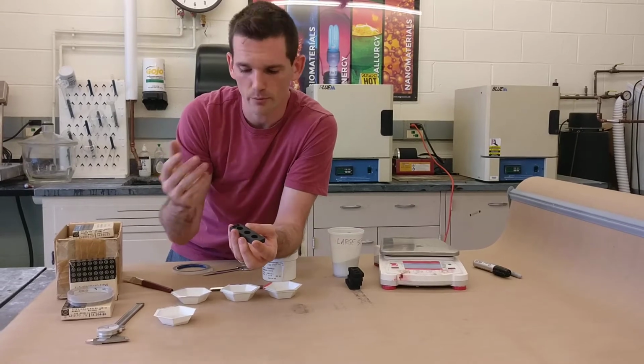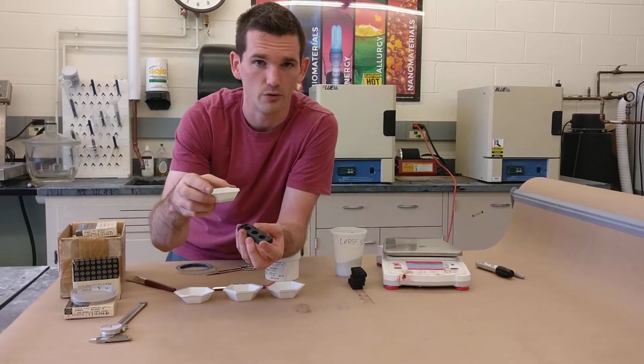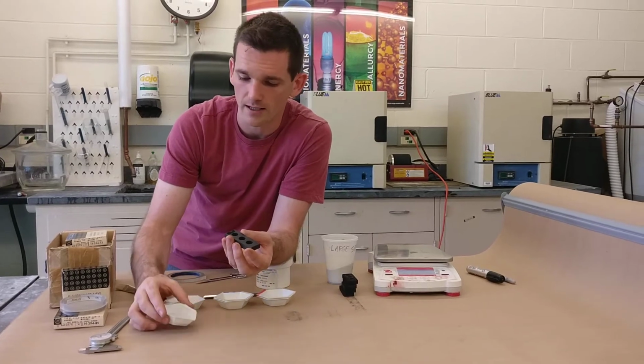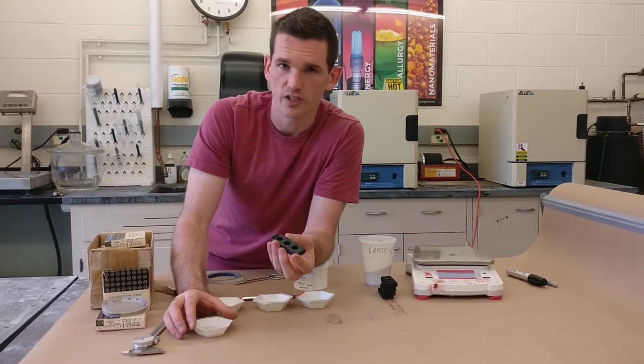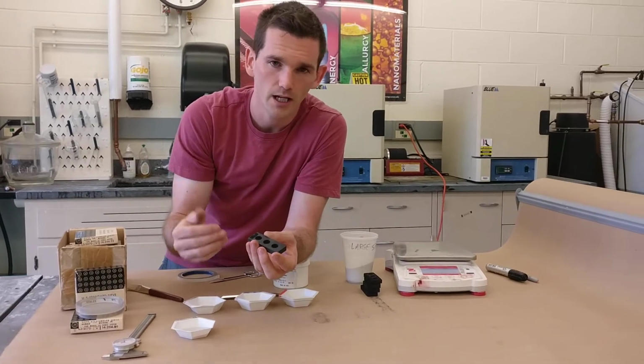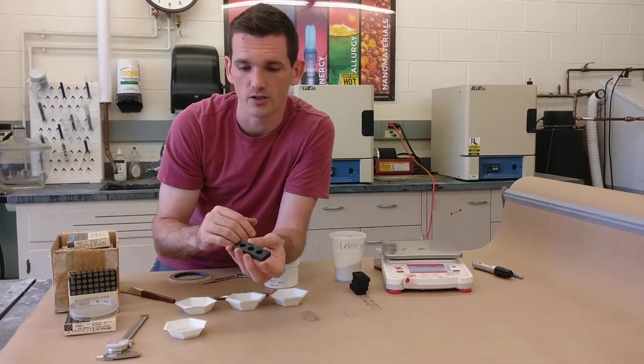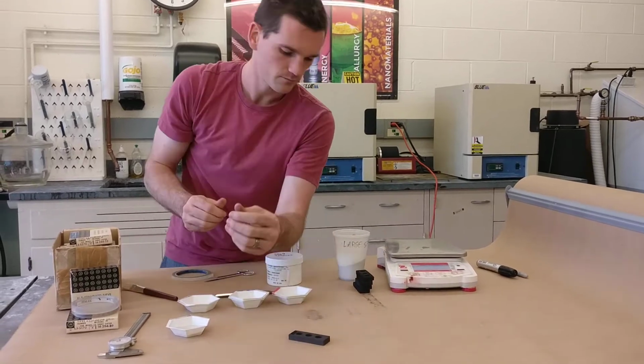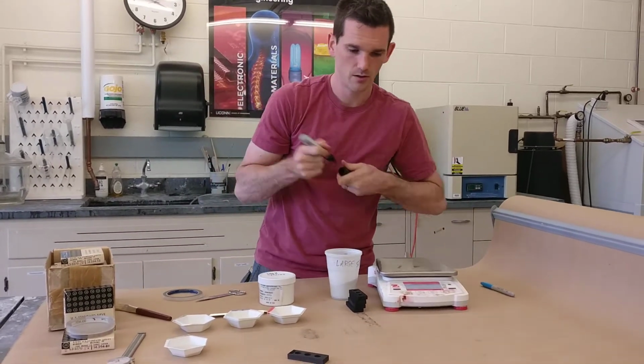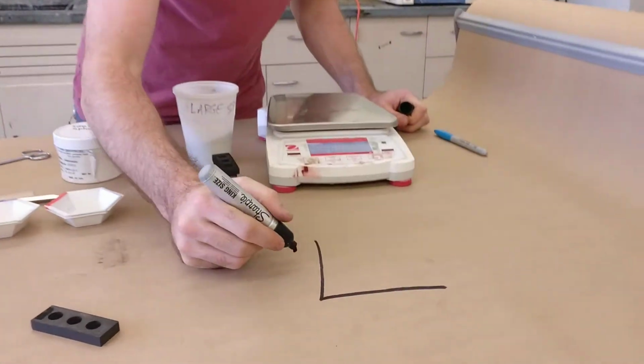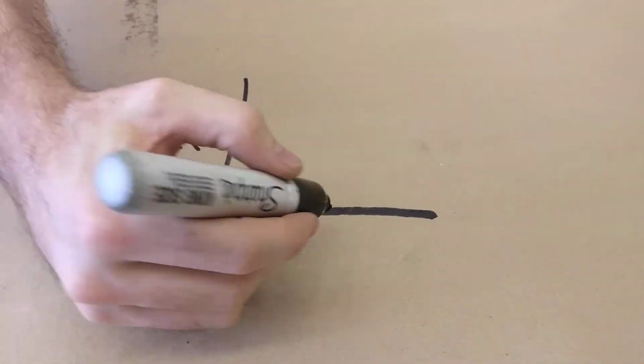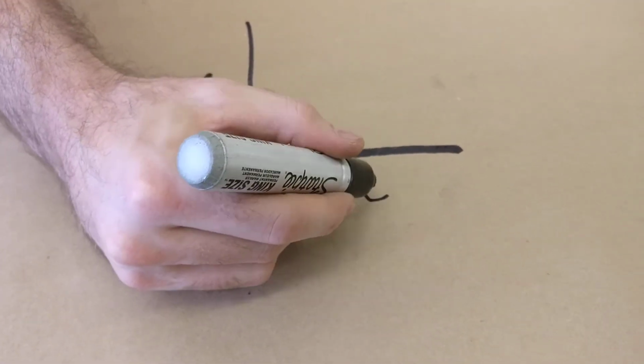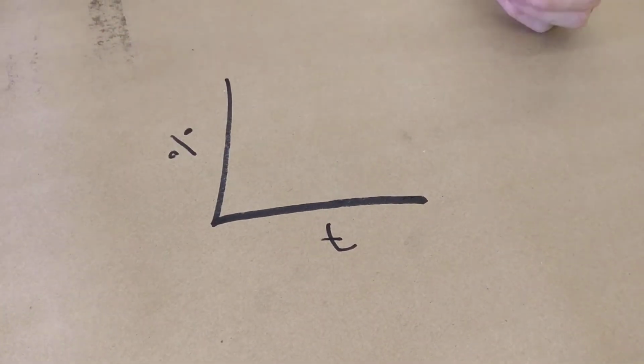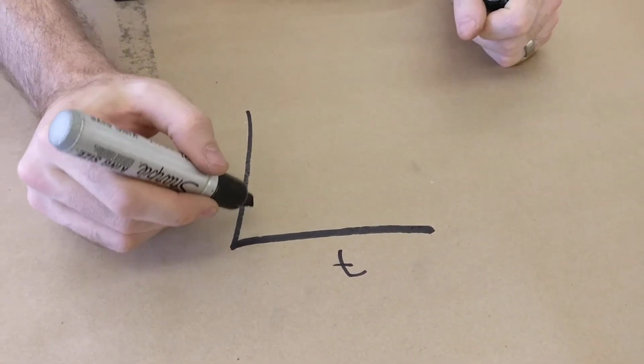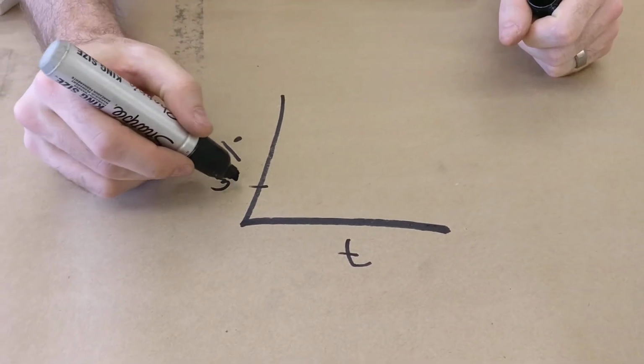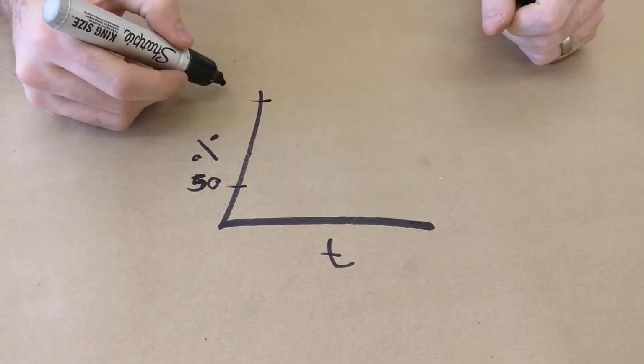So we have to divide that number by the density of this material itself, which is soda lime glass. That soda lime glass density is 2.5 grams per centimeter cubed. So whatever density you get, divide by 2.5, and that will be some percentage of density. What should happen is, if we zoom in on this, we have a chart of the percent density versus time. As we heat these things up, they're going to start from maybe 50% dense, and this is 100% dense.